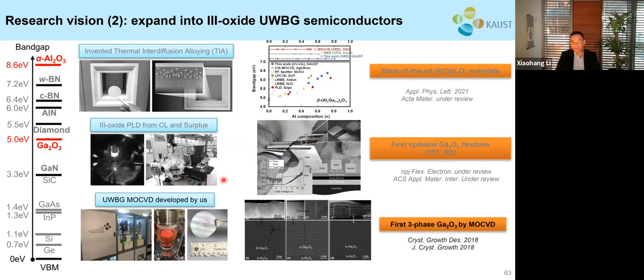In the pursuit of better ultra wide bandgap semiconductors, our group has also developed an ultra wide bandgap MOCVD that is capable of growing III-nitride and III-oxide materials. So we have utilized this MOCVD to grow and demonstrate the first three-phase gallium oxide by MOCVD, including the beta phase, epsilon phase, and alpha phase.